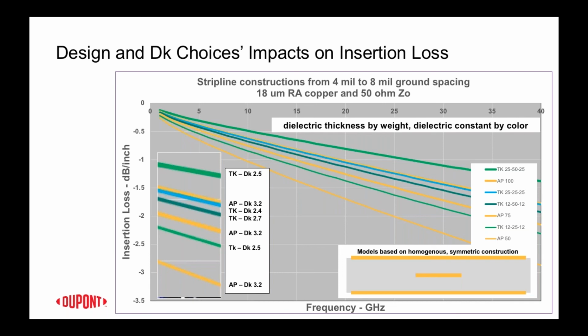So again, there are some different conductor spacings, from 4 mils to 8 mils on the ground plane spacing. That means the line width is going to vary as a function of ground plane spacing, but it's also going to change as a function of dielectric constant. Taking a look at the inset in the left corner of the graph, the Pyralux TK and Pyralux AP shown at the top of the set of curves are actually the same thickness dielectric. What separates them is the dielectric constant. And so the line width of the TK is wider, and it enjoys a better insertion loss figure